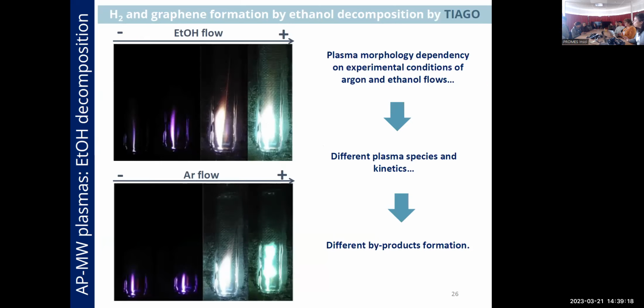Let's move now to see if the formation of the gases and the solid material is similar when we work with our plasma torch. Here in this slide, you can see different pictures of our plasma when we modify the ethanol flow from lower to higher values, and also the argon flow from lower to higher values while keeping the same amount of ethanol. You can see that the morphology of the plasma changed, and it's different depending on the experimental conditions.